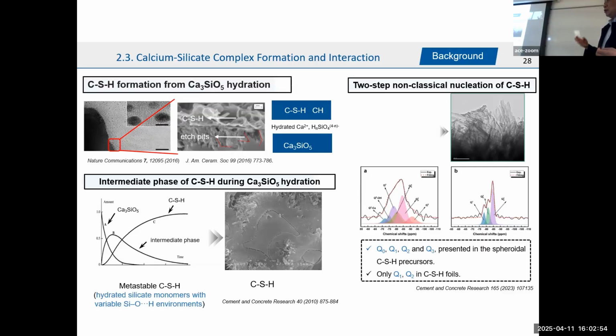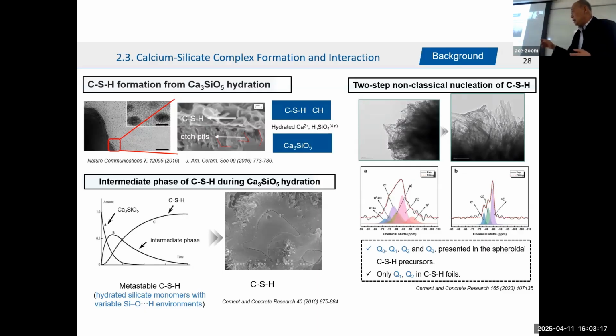based on my understanding, the CSH should be formed on the surface of the cement particle. We have a lot of examples from experiments. For example, this is a photo from one of my students from HKUST. He took a very nice photo after hydration. The C3S particle is still in there, and outside of it we have the so-called internal CSH, and outside is the outer CSH.